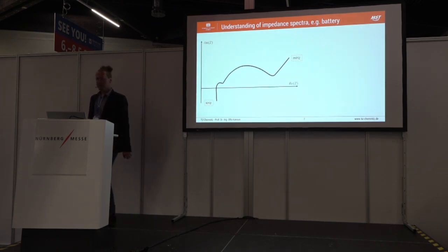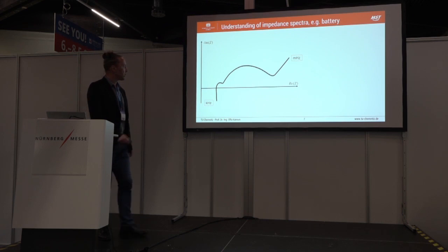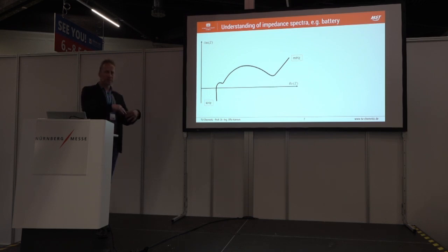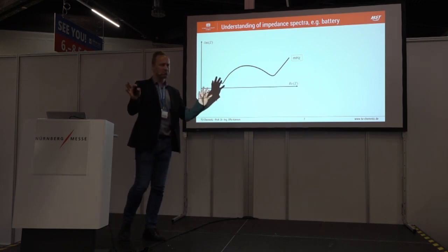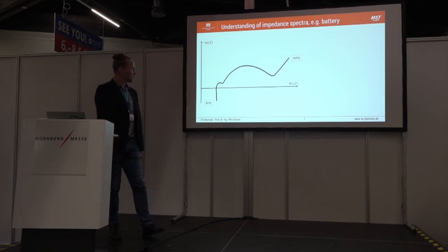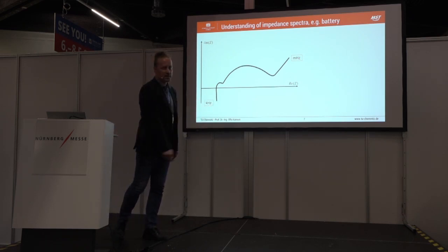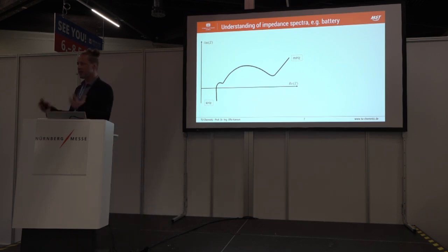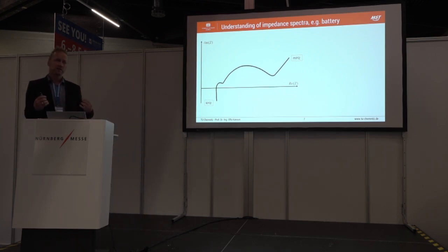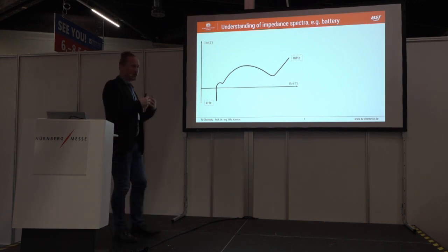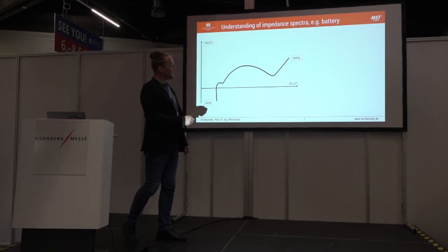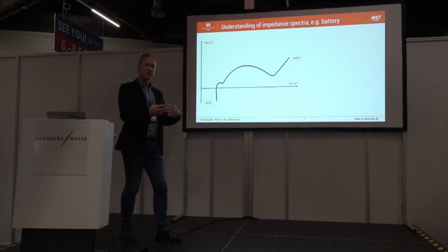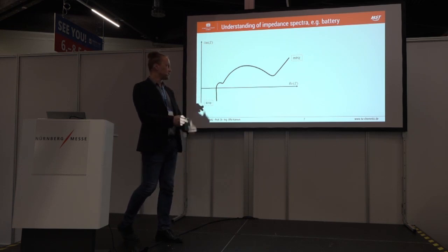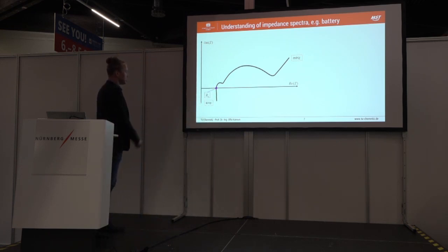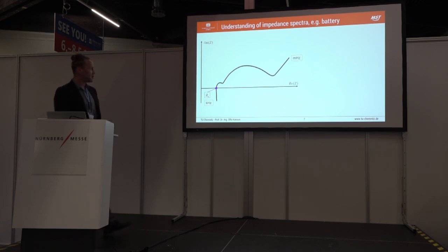But what does understanding of impedance spectra mean? You see here once again qualitatively this curve, this Nyquist diagram from the slide before. This is a typical shape, and we start here in the range of millihertz. Batteries are an electrochemical system. The effects, the phenomena are slow. You have ionic charge transfer. That's why you need low frequencies to analyze this range or these phenomena. We start here. This is the so-called RS point, the shift of the real part.